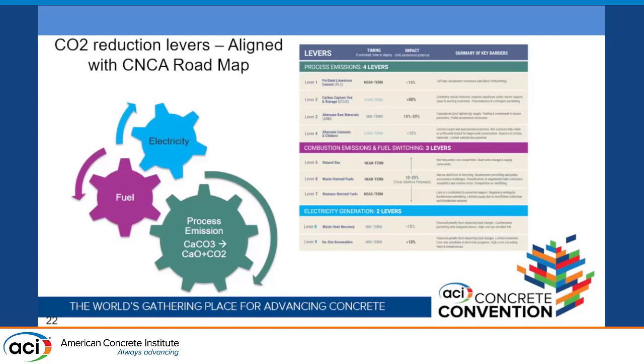So up here, the first lever, the Portland limestone cement, that's the low-hanging fruit, as you could say. That is reducing the clinker factor. One way to reduce the clinker factor is just to replace that with limestone. And you can get about 10% reduction in your global warming potential for your EPD.